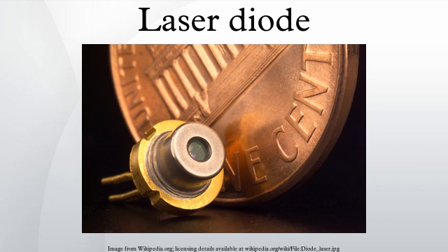At the edge of a diode laser, where light is emitted, a mirror is traditionally formed by cleaving the semiconductor wafer to form a specularly reflecting plane. This approach is facilitated by the weakness of the 110 crystallographic plane in III-V semiconductor crystals compared to other planes. A scratch made at the edge of the wafer and a slight bending force causes a nearly atomically perfect mirror-like cleavage plane to form and propagate in a straight line across the wafer.